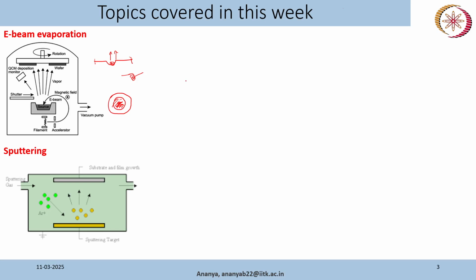at the time when you know that the thickness you have already achieved is 50 nanometer, if that is your target. You don't want your thickness to vary in a very large range. Say 50 plus minus 5 nanometer is okay, but you don't want your film thickness to be 70-80 nanometer. In that case, using a shutter, you can get a film that is of your desired thickness. Now again, you have to be careful with the deposition rate. If the deposition rate is very fast, even if you close the shutter, there will be a little bit of extra deposition during that time also, that will change your film thickness.